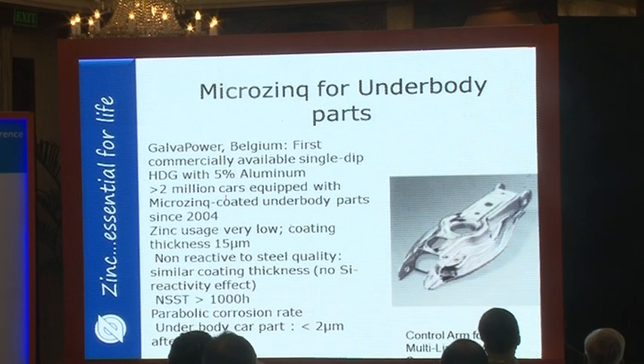There's also a product called MicroZinc. This is a Voigt & Schweitzer product. GalvaPower is the subsidiary, and this is now in series production. This shows a multi-link BMW suspension. This is a zinc 5% aluminum hot dip coating, and they've trademarked it MicroZinc, and this uses about a 15 micron coating thickness. So it's much lower thickness than our normal coating thickness that we would have on a hot dip galvanized part.